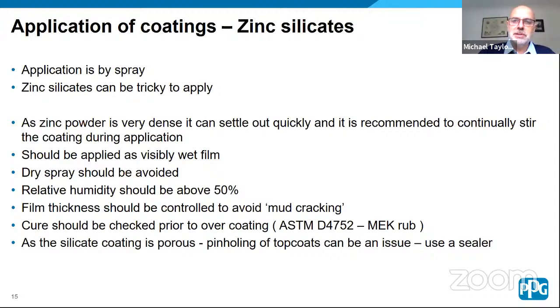The film thickness should also be controlled to avoid something called mud cracking, which I'll show in the next slide. But if you imagine the bottom of a riverbed that's dried out, this is when you over apply the coating. The recommended dry film thickness for zinc silicates is typically between 50 to 75 microns. If you get up to 100 microns and above, you can get this mud cracking occurring. And the cure should be checked prior to overcoating.